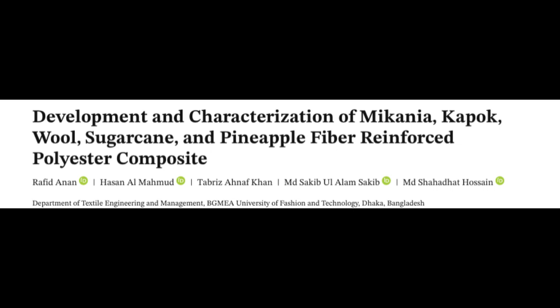Good analogy. So, what did they discover when they put these natural fiber composites to the test? Let's start with tensile strength. Which one could handle the most pulling? The results showed that the composite reinforced with pineapple fiber was the strongest in tension. Really? Pineapple? Yeah, reaching a maximum stress of over 42 megapascals. It also showed the most stretch before breaking at over 4%. Wow. So surprisingly, pineapple really stood out in its ability to resist being pulled apart. That's not what I would have guessed at all.